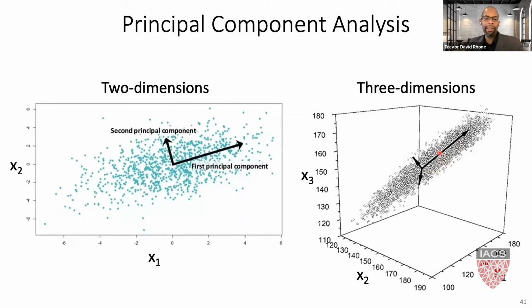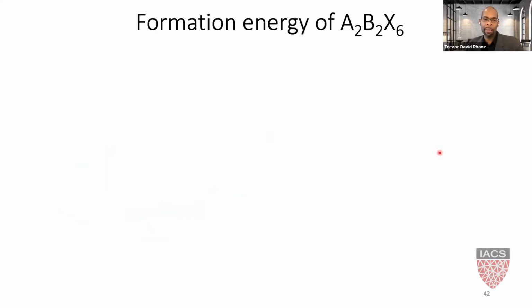Okay, now we don't only care about whether the material is magnetic or not. We also care about making it and not having it fall apart in the lab. So we need to have these materials being chemically stable. And it turns out that formation energy is a good proxy for chemical stability. So we've also calculated formation energy for the materials, and we can do analysis on the formation energy and try to make machine learning predictions for that as well.